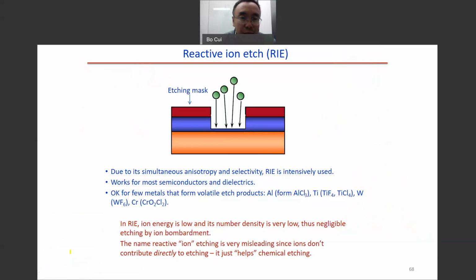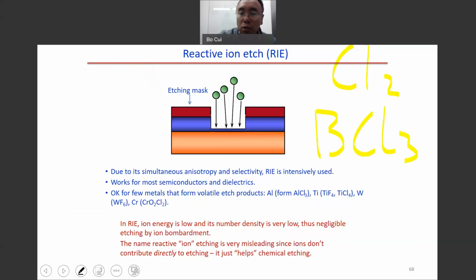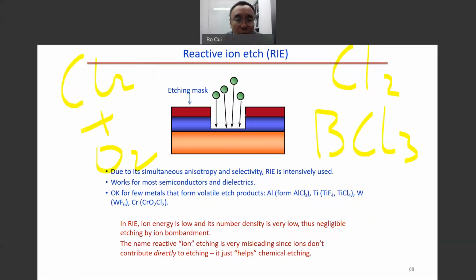But for the metals, most metals cannot be etched, but some metals can be etched. For example, we can use chlorine gas or BCl3. So we can use those gases to etch aluminum and also titanium, as well as fluorine gas for titanium and tungsten. For the chrome, we have seen that we can use a mixture of chlorine gas and oxygen gas to etch the chrome. But many other metals will be very difficult to etch. For example, nickel.